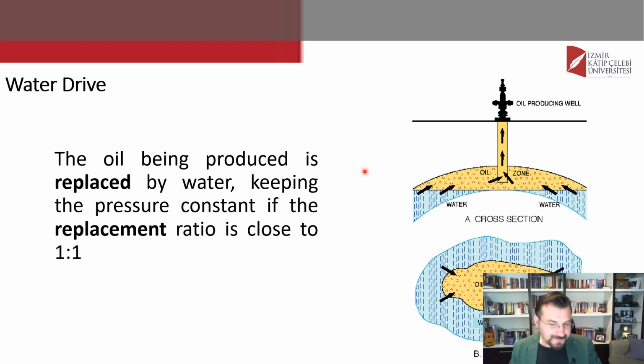So what you need to do, for example, if you have 500 wells in a field, is describe which parts show the conical behavior, make some cuts and lower your production in those parts, and open the parts showing less for oil production, and balance it. This gives you an opportunity to manage your water phase, your aquifer zone, without creating conical behavior and increasing the water production.